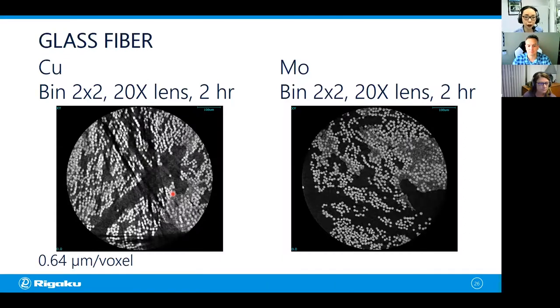And you don't see that when you use molybdenum, 17 keV. This is a scan we saw in part one when we're using molybdenum. You have a good contrast between the resin and the glass fibers and the air, and you don't see any sign of beam hardening artifacts. So you got this one right. Molybdenum works better for glass fibers because they're more absorbing. The density is about 2.4 grams per cubic centimeter.